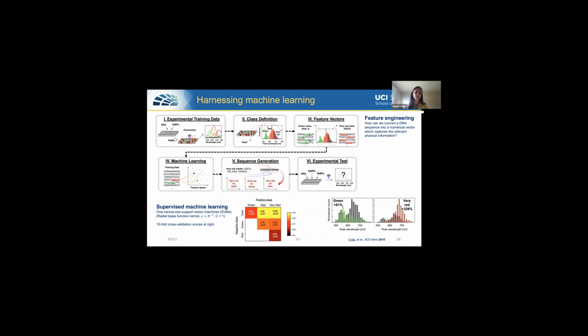When we used our trained algorithms to design green clusters, we would expect them to be within this region of the histogram. We were able to, with some modest success, concentrate most of our designs within that green region. We were much more successful moving out into the near infrared, with this so-called very red class. So this was exciting.